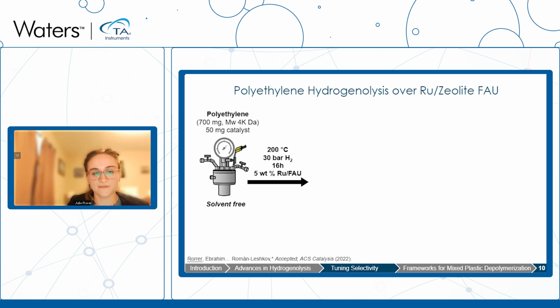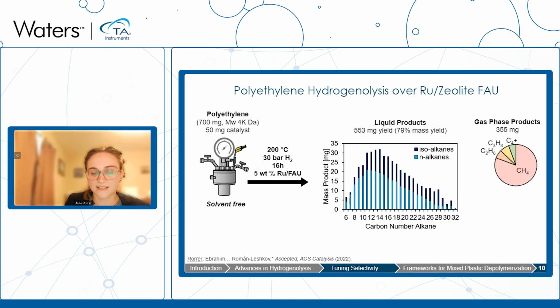So zeolite faujasite, FAU, is one of the catalysts that we studied, and this has high Bronsted acidity and also a nice pore structure that we can tune. And so by supporting the ruthenium nanoparticle on this faujasite, we can run the same reaction as the ruthenium on carbon that I showed you earlier at 200 degrees C under 30 bar of hydrogen. And this time we actually get a 79% mass yield of liquid products, and we still get some gaseous products with methane and light alkanes as well.